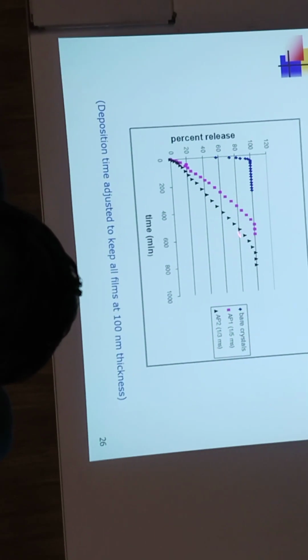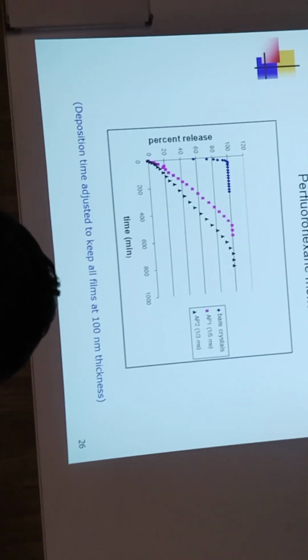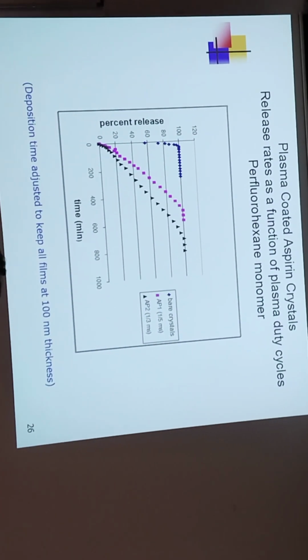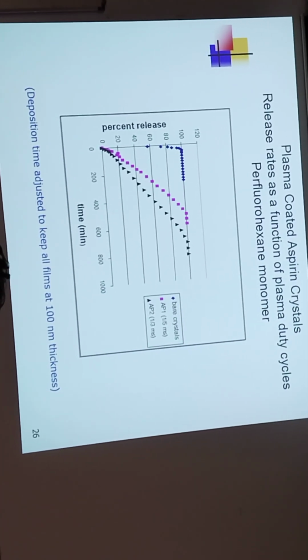Similarly, we coated aspirin crystals. Bare aspirin crystal was released immediately, whereas aspirin crystals coated with the pulse of 1 millisecond on, 5 millisecond off, show the release rate you can see. And further, we varied this duty cycle, 1 millisecond on, 3 millisecond off. It means the film is more cross-linked, and because of that the release is slow, so we can control the release rate. This is a kind of sustained release, and the drug is available for a longer time for absorption instead of 2-3 times a day. Probably 2 times a day would be sufficient because it's sustained release.